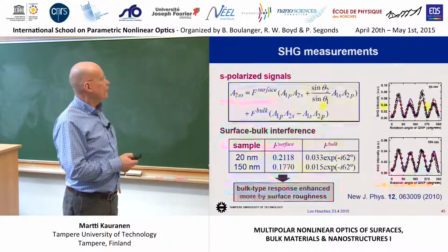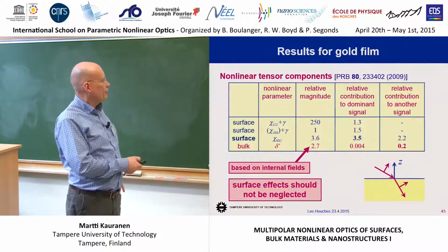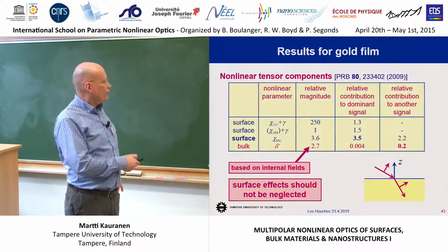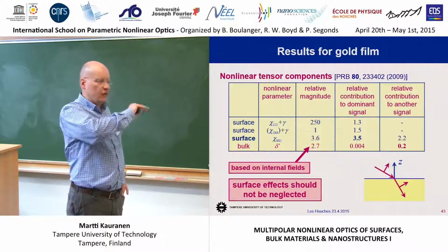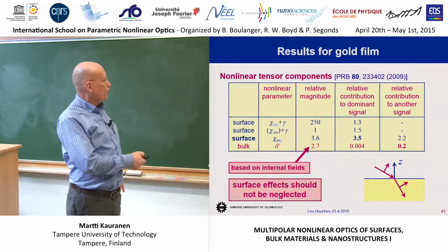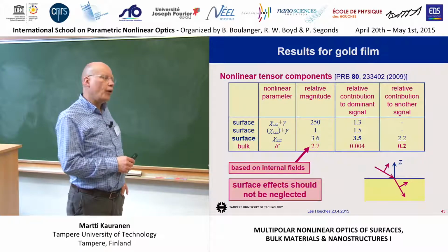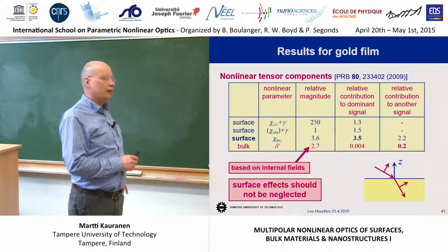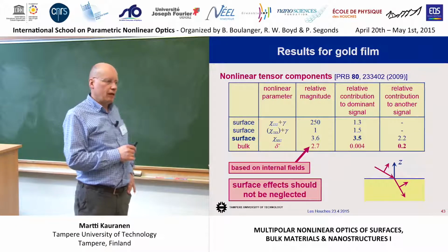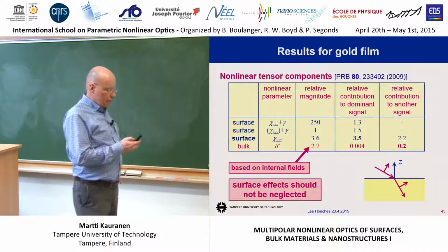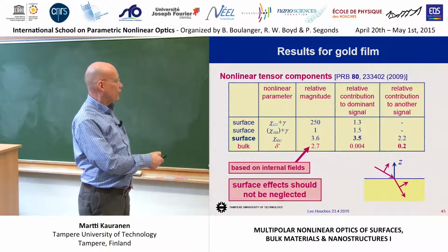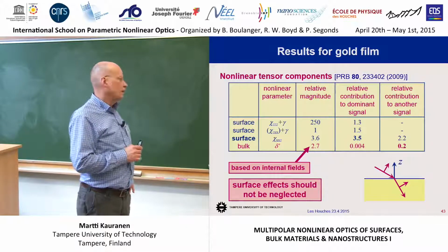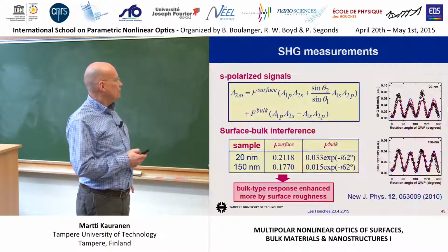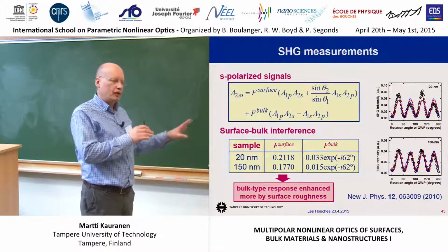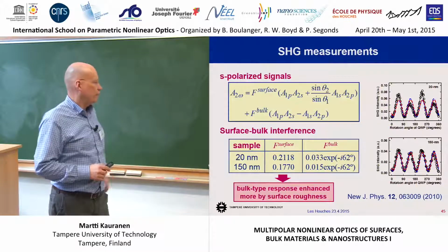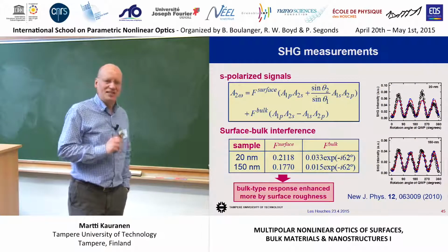On the other hand, I forgot to say that these results from the gold film, we also calibrated against a reference sample, and the numbers we got for these various parameters are amazingly close to theoretical predictions from John Sipe's free electron model. The biggest uncertainty in this delta prime parameter was a factor of 10 higher than we hoped it would be. But the fact that there's always a surface roughness also plays a role here. That could have influenced the results there. So it's not easy, not easy.